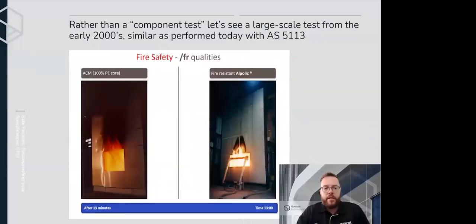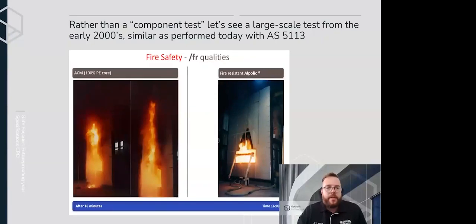This is 13 minutes in, and the facade panels on the left are well and truly alight and contributing to fire. ALPOLIC FR on the right, you can see that the panels are being damaged, but they aren't actively contributing to the spread of fire. Now this is 3 minutes later, so you can see here that the facade is well and truly alight and is starting to drop some of that flaming debris down. Now this is how polyethylene fires can spread so quickly around a building.